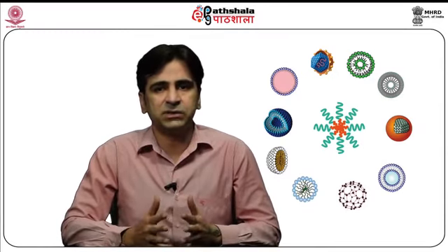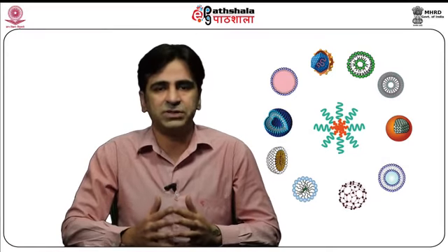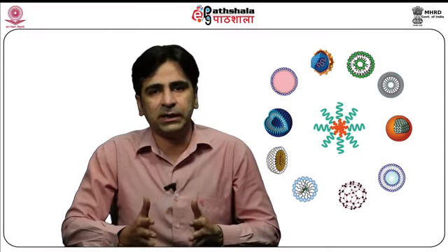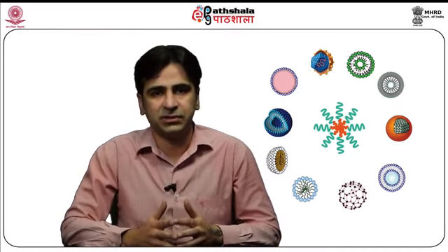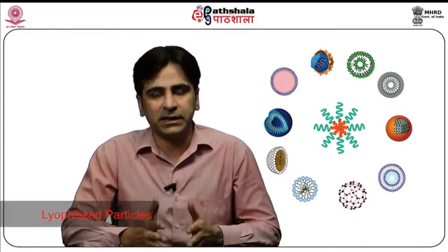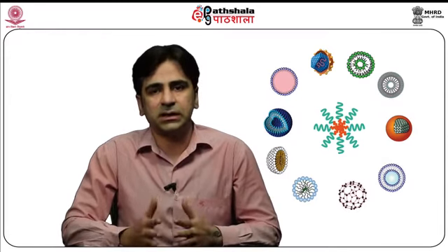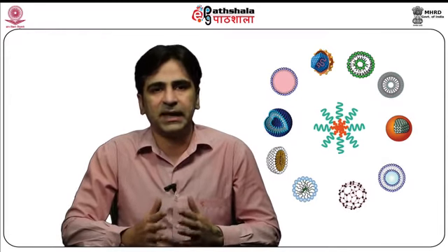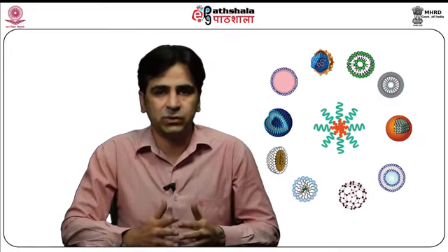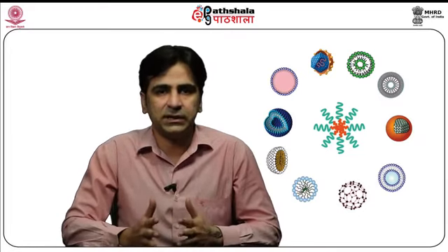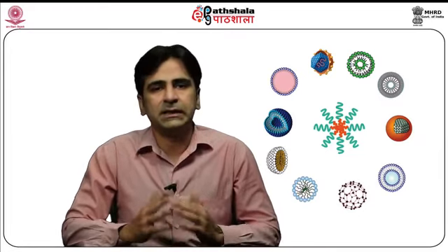Now come to the direct method. Nanosuspension is subjected to centrifugation followed by washing of the pellet and subsequently lyophilization of the formulation. After that, lyophilized particles are dissolved in a common solvent in which both the drug and polymer are soluble, and then samples are subjected to analysis for drug content using a suitable analytical technique.